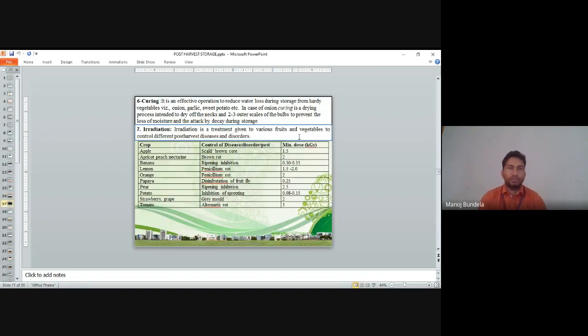Next is curing. Curing is an effective operation to reduce the water losses during the storage from the hardy vegetables like onion, garlic, sweet potato. In that we have to go for curing. In case of onion, curing is a drying procedure intended to dry off the necks and 2 to 3 outer scales of the bulbs to prevent the loss of moisture and attack by decay in the storage.